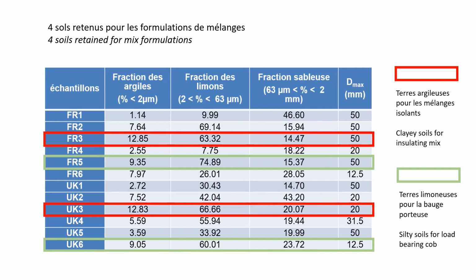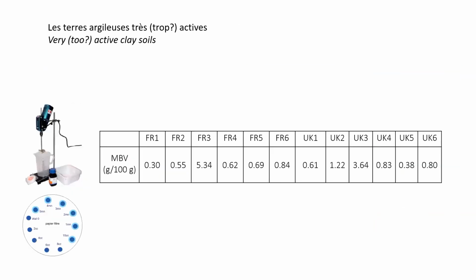And soils that were more clayey, that we then decided to keep for the light earth mixes because they had a strong cohesion strength. So the lab studies were quite extensive, and we also analyzed the different types of clay, and we realized that some of the active clay soils we'd chosen were very active or sometimes too active, and that could have led to various issues.